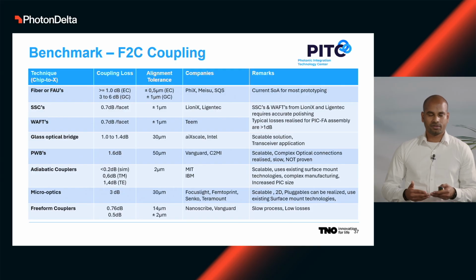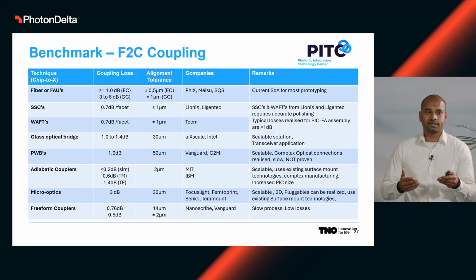At the end, we also have freeform couplers, where there's a 2-photon polymerization technique introduced by Nanoscribe and Vanguard, where you can easily print your lenses on top of the PIC or a fiber array, and have the chance to play with the coupling loss and alignment tolerance. The best alignment tolerance proven so far with this technique is about 14 micrometer with 0.76 dB losses, and the best coupling loss proven is about 0.5 dB with plus or minus 2 micrometers.